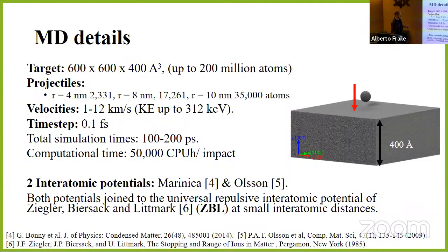The time step has to be short, 0.1 femtoseconds, to conserve the energy in the simulation. And the total simulation time is 100 picoseconds. In some cases, we double-checked with 200 picoseconds to see if everything is stable and equilibrated. So these are very heavy simulations and computationally very expensive. Every simulation was about 50,000 CPU hours.